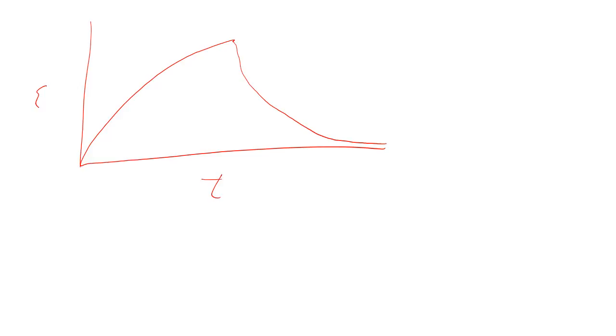The big problem that everyone who did this approach made was they forgot one thing: the Boltzmann superposition. So this part keeps happening on and on forever, and they forgot the initial instantaneous elastic response.